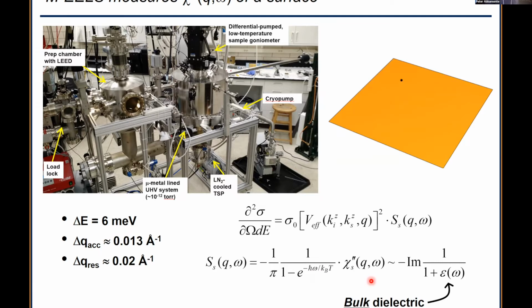But for example, if the system is Q independent, if the response is Q independent, you can show this is just the imaginary part of 1 over 1 plus epsilon. So it's almost the imaginary part of 1 over epsilon. And importantly, epsilon is the bulk dielectric function. So it's not really a surface probe in the same way as STM. It's more of a bulk probe of a semi-infinite system where you have to consider the fact that there's an interface that you have to interact with to get data.